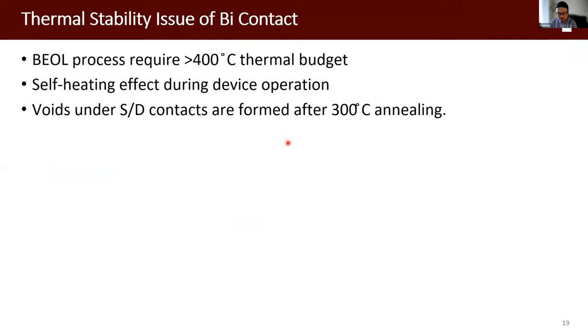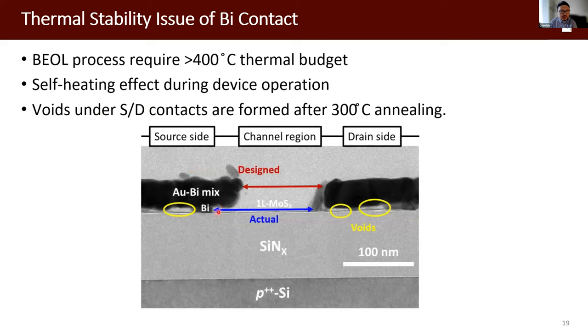So we demonstrated a very good performance, but at the same time, there's an issue related to bismuth. For any back end of line fabrication process, usually the temperature needs to be very high, so we need to design a thermally stable contact strategy. And also during the device operation, there are self-heating effects. The true heating during the operation may also introduce a much higher temperature. If the thermal stability is bad, we could also degrade the device. So in our experiment, we can see after 300 degrees Celsius annealing, the interface becomes very bad. A lot of voids are formed between the bismuth and the MoS2 interface.